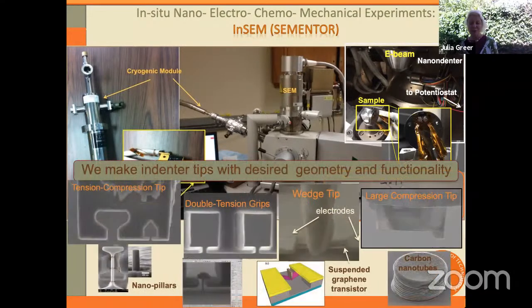And so these are the so-called different in situ devices that we use. So what you see here are, for example, different grips and different compression tips that we use. The spacing here is about 200 nanometers. So we can pull on a pillar that's only 100 nanometers in diameter or below. So we can handle very small length scales, as well as the micro scale right here. So this is what you see here with this much larger indenter tip.